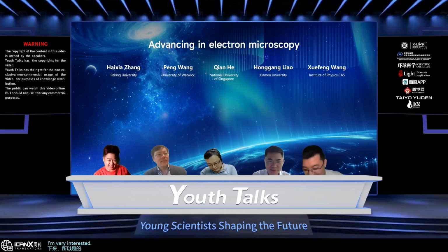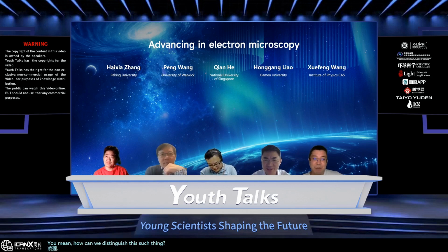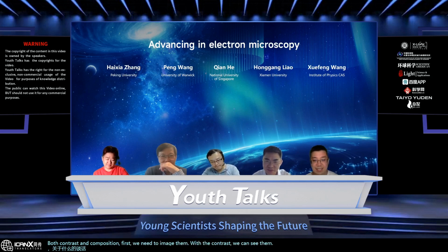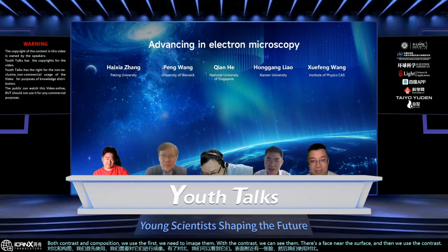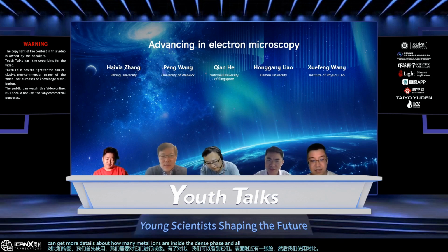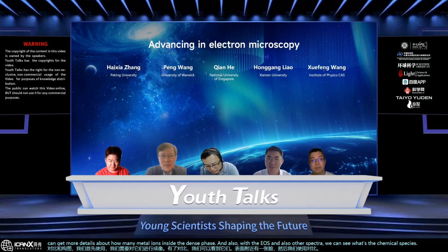I'm very interested in the liquid TEM, especially to understand or to propose the electric double layers. So the first question is, how can we distinguish such thin layers? You mean how can we distinguish such a thin layer on the surface? Based on both contrast and composition. First we need to image them. With the contrast we can see that there's a dense phase near the surface, and then we use STEM mode to analyze them. With STEM, we can get more details about how many metal ions are inside the dense phase, and with EELS and other spectra, we can see what kind of chemical species are inside.